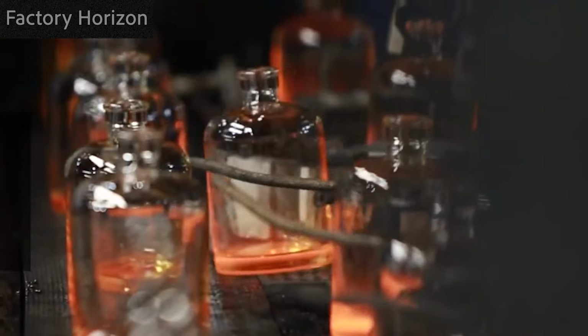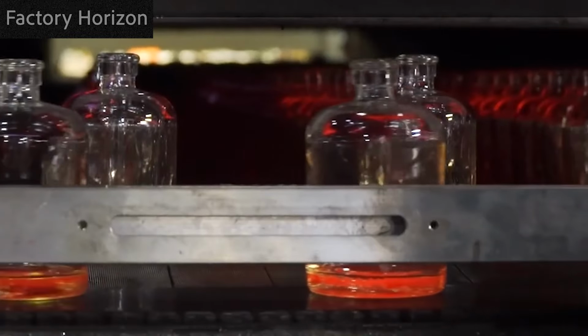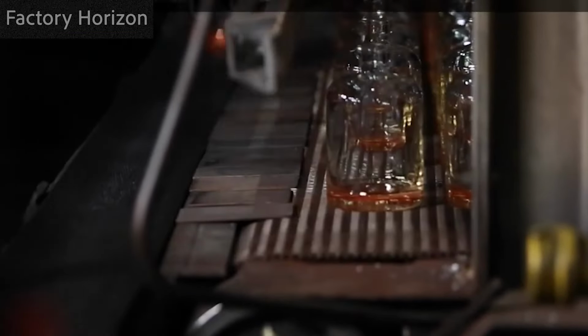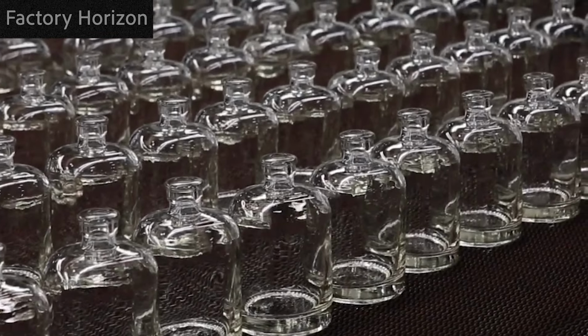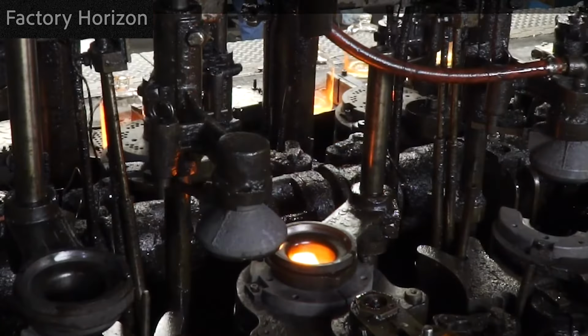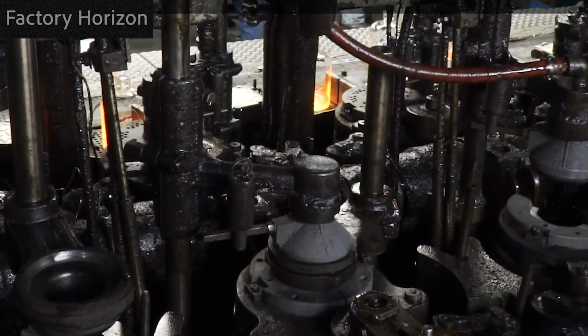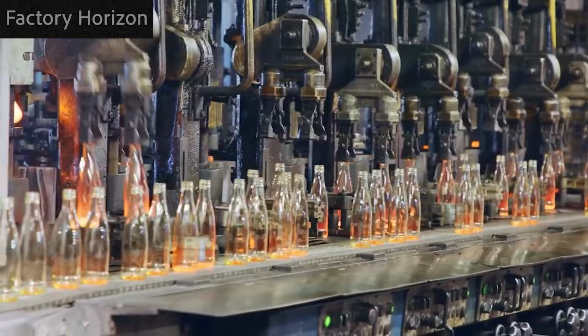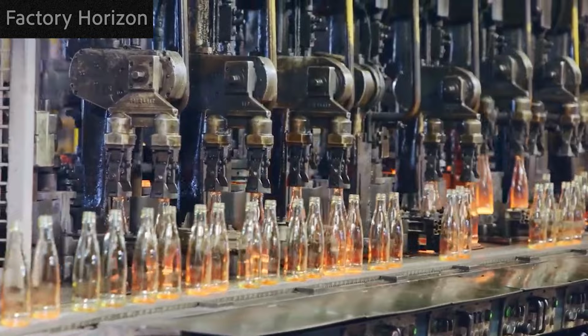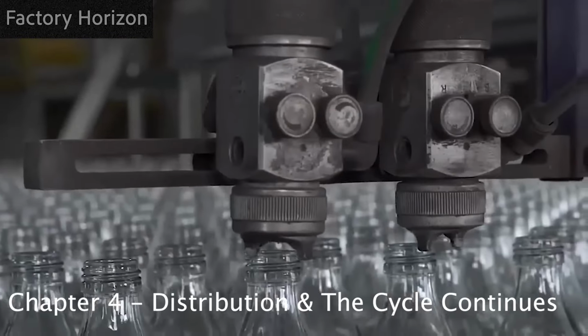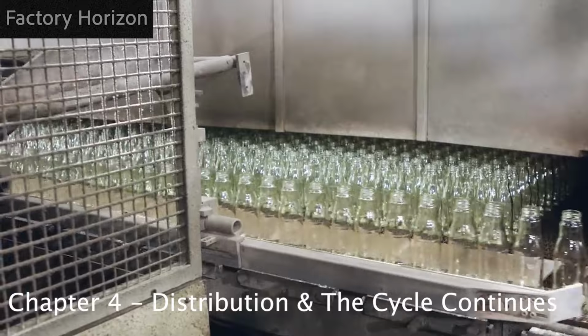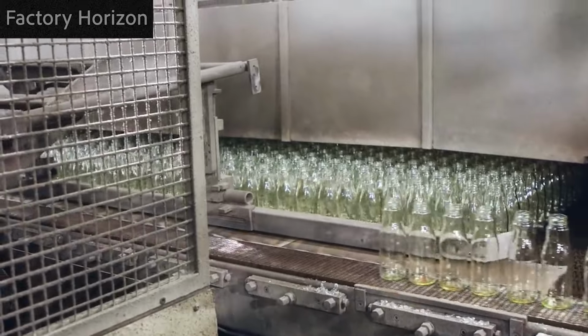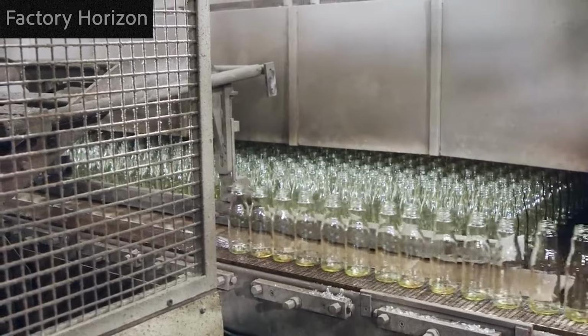The annealing tunnel provides continuous real-time inspection as newly formed products cool gradually. This tunnel stretches over 100 feet long and reduces glass temperature from 1,000 degrees down to safe room temperature over approximately 20 minutes. Cooling too rapidly locks in dangerous internal stresses that cause bottles to shatter spontaneously days or weeks later. Finished cullet and newly formed glass products converge in the massive shipping warehouse, where the recycling circle finally completes itself.